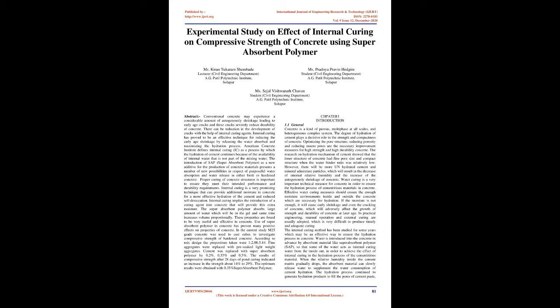In the current study, M25 grade concrete was used to cast cubes to investigate compressive strength of hardened concrete. According to mix design, the proportions taken were 1:2.08:3.44. Fine aggregates were replaced with pre-soaked lightweight aggregates. Cement was replaced with super-absorbent polymer by 0.2%, 0.35%, and 0.5%. The results of compressive strength after 28 days of pond curing indicated an increase in the strength of about 14% to 29%. The optimum results were obtained with 0.35% super-absorbent polymer.